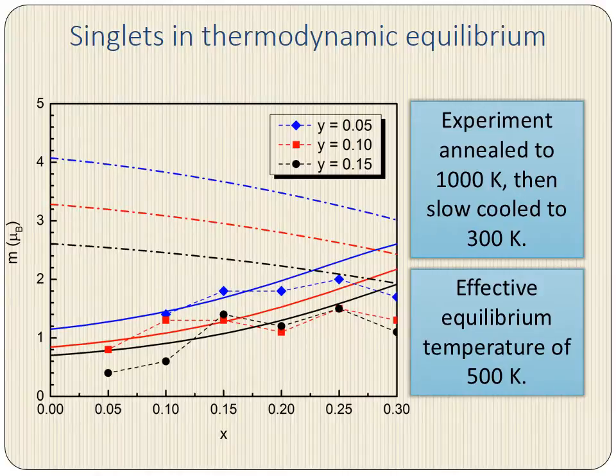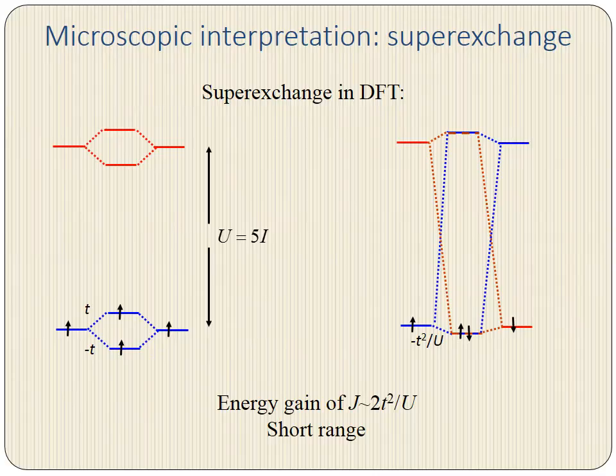So what we see here is that the magnetization of a sample depends on the thermal protocol, and so we predict, for example, that quenching the system, as opposed to slow cooling it, could lead to enhancements in the magnetization as high as 3 Bohr magnetons.